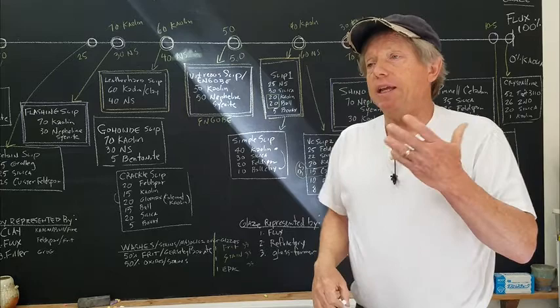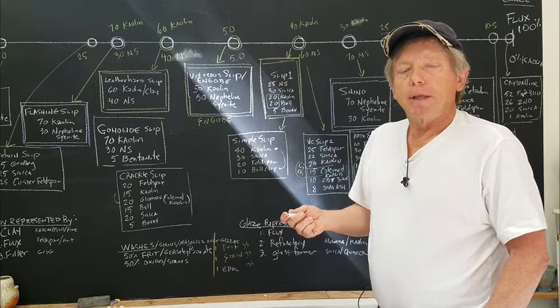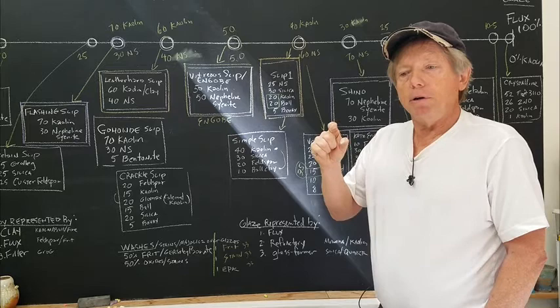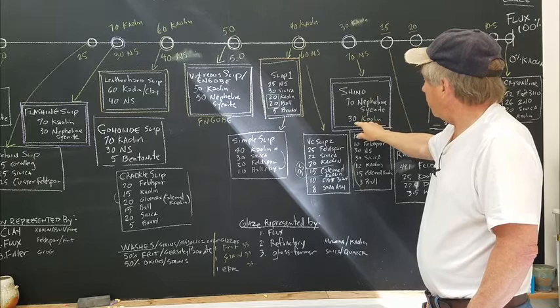And then Shinos will use a variety of feldspar. So they won't just use nephsi. They'll use spodumene and soda feldspar, like minspar and nephsi. So they have three feldspars, and then they'll do them in different percentages. And then for the kaolin component, they may use kaolin if they want it whiter, or ball clay if they want more iron, or they could use earthenware clay. So all this, but this just gives you a general idea of a Shino recipe, 70-30.